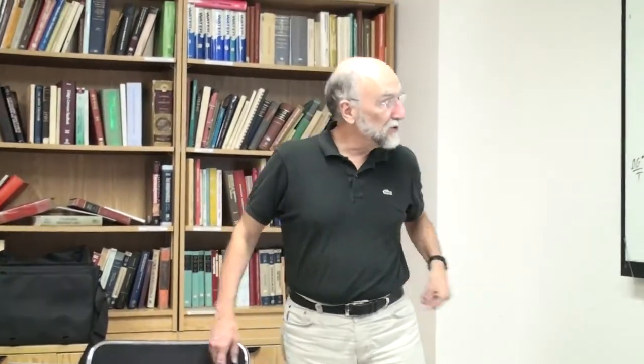And this is why you will see in the materials science and metallurgical literature the heat capacity measured in the area of 2, 3 to 10 Kelvin. You would wonder why anybody would care what the heat capacity was down there. This is why: if you can measure it accurately down there and extrapolate the last few degrees to 0 Kelvin, you can obtain the absolute entropy for the substance. And this is very useful.